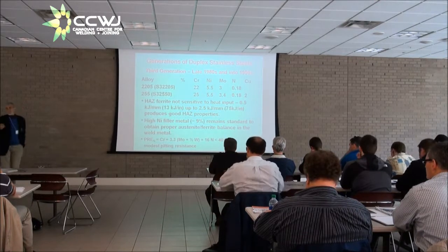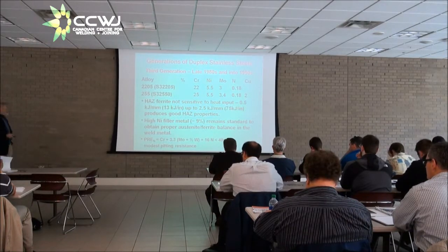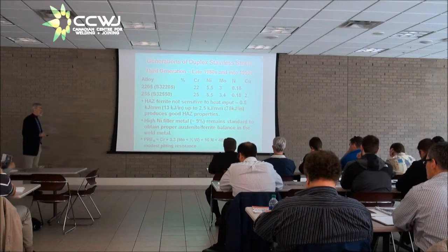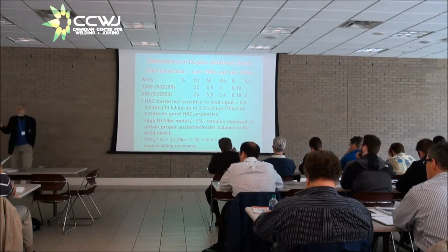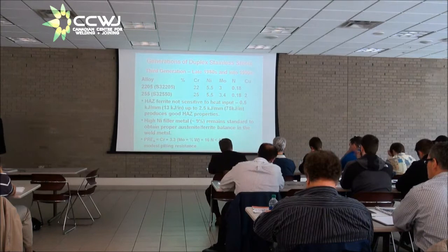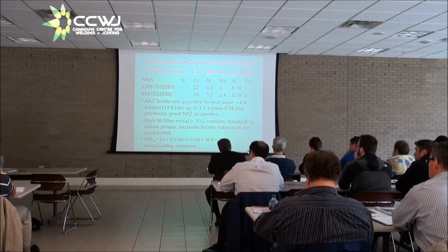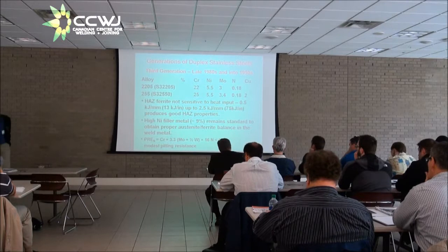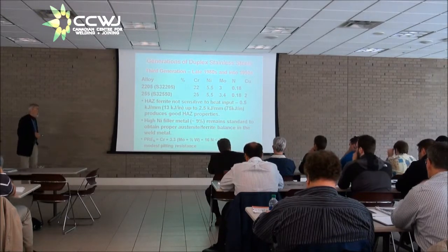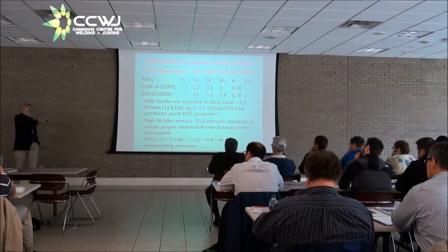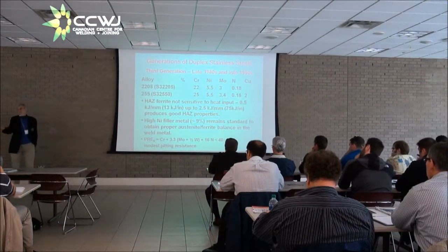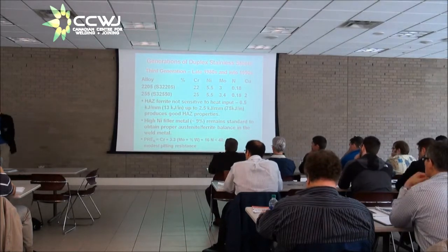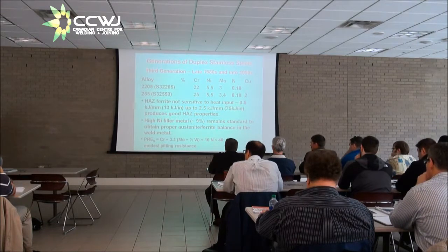And I'll give you a slightly different version of the pitting resistance index because there's a factor for tungsten in it. I think when you saw the one this morning, you saw it without tungsten. Tungsten is considered to be half as effective as molybdenum in terms of providing resistance to pitting. Otherwise, for a tungsten-free alloy, the pitting resistance index calculated this way is the same as the way you saw it this morning. But for 0 and 100, which contains deliberate additions of tungsten, this matters.